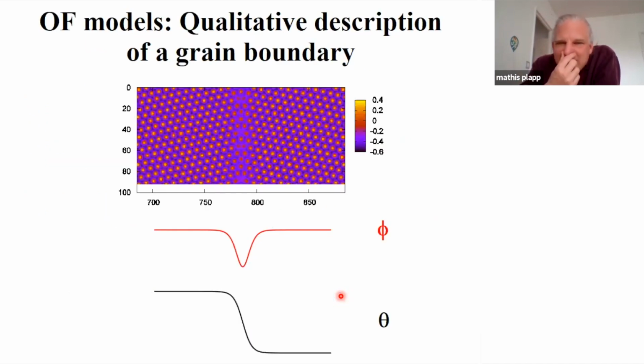To give you an idea how this should look, here is a density functional calculation of a grain boundary. You see two hexagonal 2D crystals on the two sides that have a different orientation, and in between you have a grain boundary. And as you can see from the color code, the order is more pronounced within the grains than in the grain boundaries, clearly because the positions are disordered.